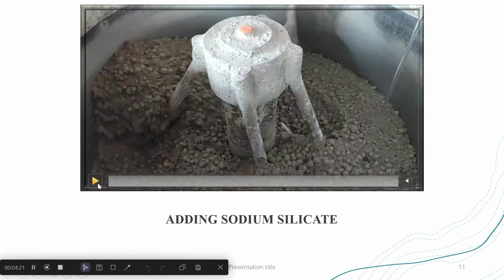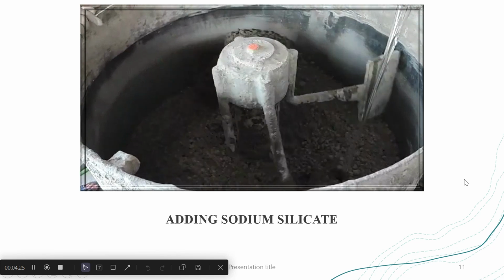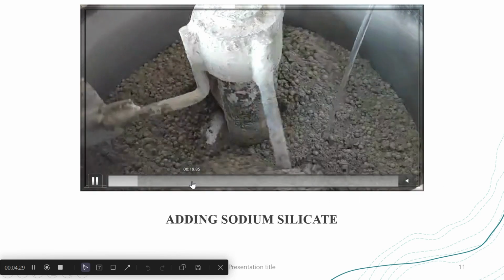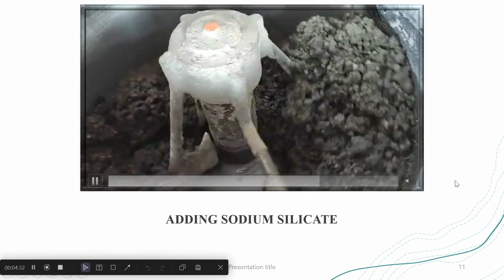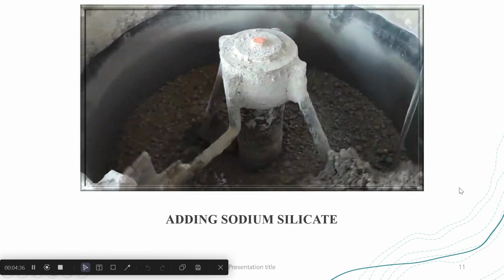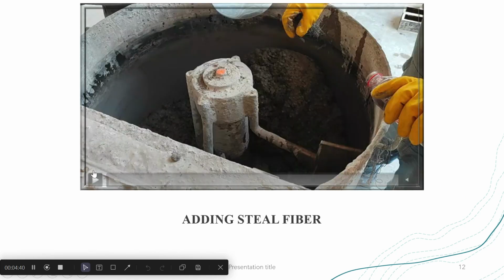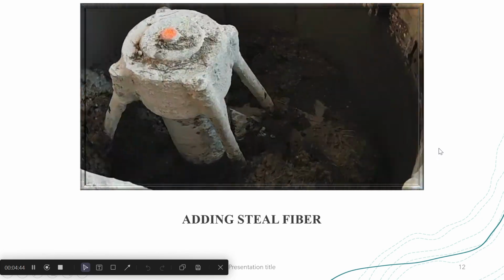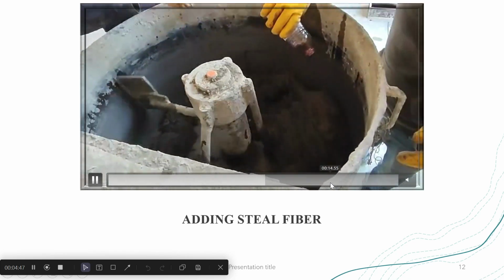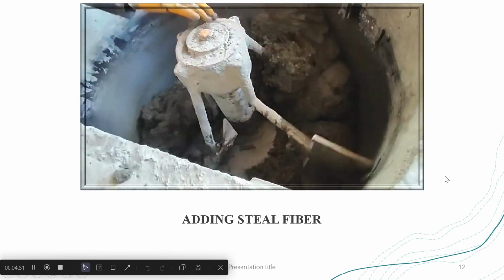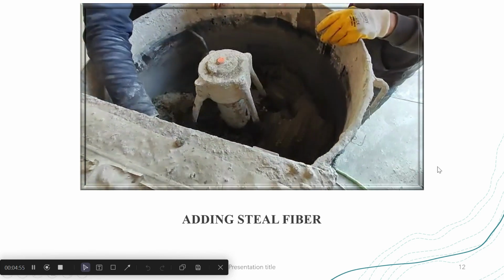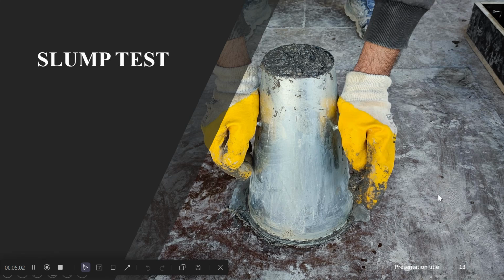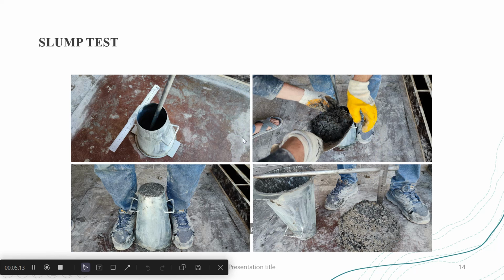Let me show you the mixture. This is adding the sodium silicate to the mixture. And after that, adding the steel fiber to this mixture. We have two types of concrete: concrete with steel fiber, and concrete without steel fiber. After the casting, we did a slump test to check the workability of this mortar, as you can see in this slide.